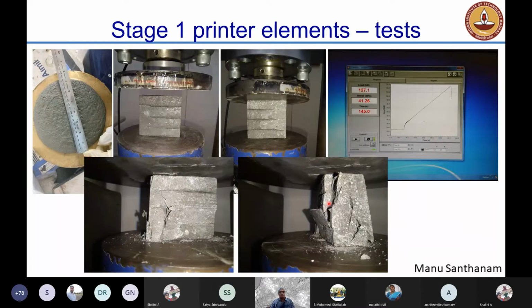Now, the issue with testing is always a challenging one because in normal concrete, you can always make cubes or cylinders and test the strength. But here, how do you bring in the effect of the interface in there? So you need to probably start thinking about methodologies that are similar more to masonry. Of course, with fresh properties, you can test the flow test. Okay. You can establish the relationship between the flow and the vane shear, the yield stress measured by vane shear, and use that for your design purposes.